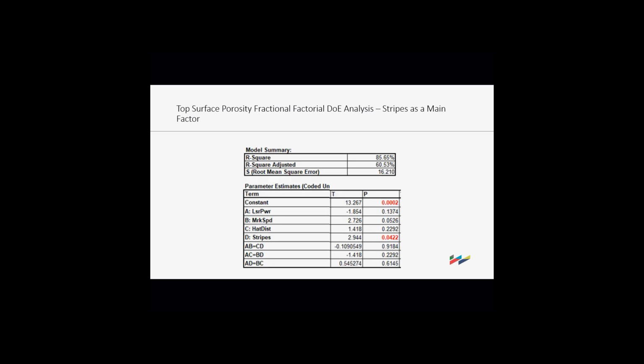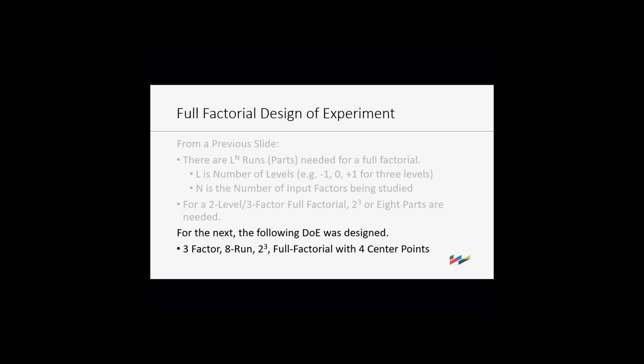Okay? Then we did a top surface one, and so we had stripes as the main factor in causing the response in that middle zone I was showing before. And again, the constant is there. But that shows that different responses can have different factors or interactions involved. We've gone through this before, so the next DOE was the 3-factor 8 run, which we talked about very early, full factorial with the 4 center points.